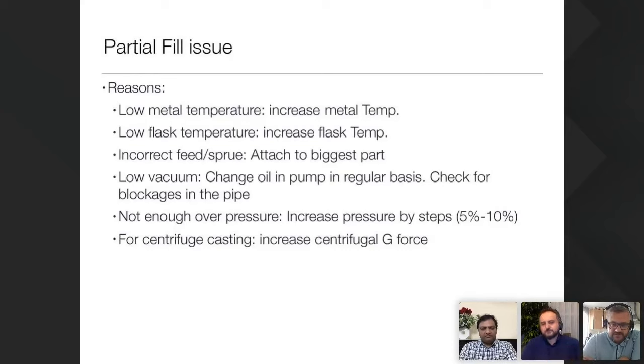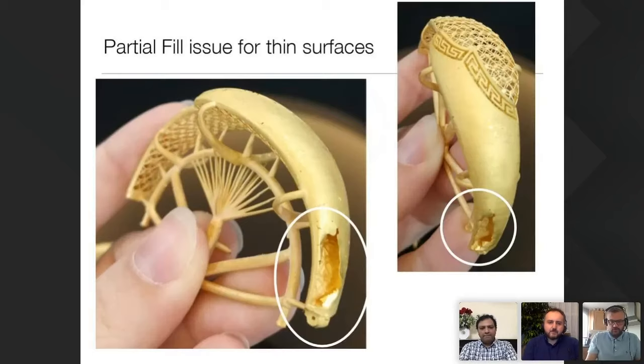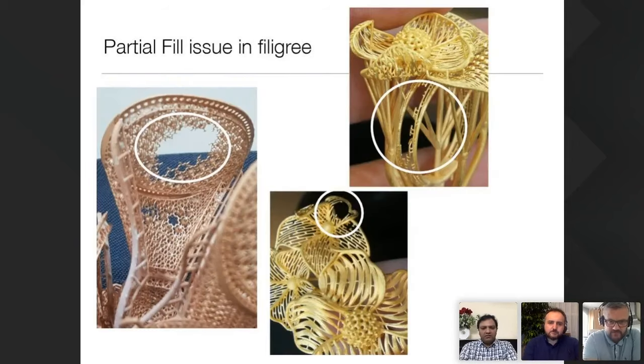If the sprue is not sufficient, if the feed is not sufficient for the part, then if the sprue is very thin, it's going to cool. If it's going to cool, it's going to set, and then none of the liquid metal coming after can enter and fill your parts. So the feed is also very important.